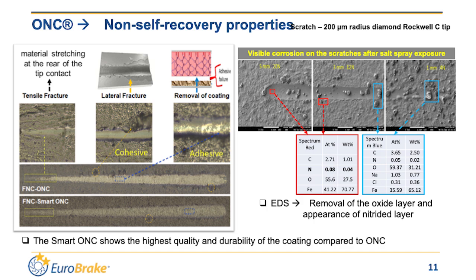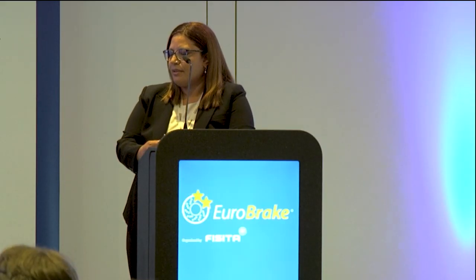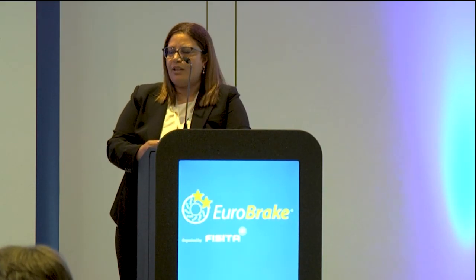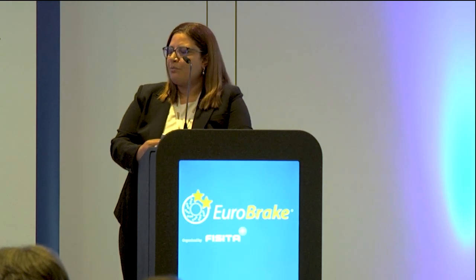The scratched sample was put in salt spray. After several hours of exposure, with the scanning electron microscope we can see that there is visible corrosion that appears on the scratch and around it. And with chemical analysis, we can see the existence of nitrogen and carbon, which indicates that the oxide layer was removed and the nitride layer was exposed. While for the FNC Smart ONC, it shows superior protection against these failures, which indicates an improved